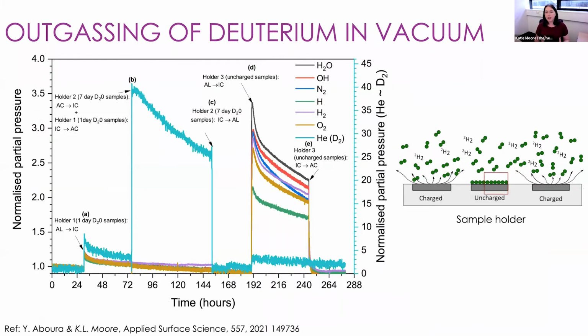As I said, Yasser's project was to really try and look at what we could understand from the NanoSIMS and what we could believe and what we couldn't believe. And I also mentioned at the start that we do not have a cryo stage on the NanoSIMS. So one of our major concerns was that before we could even analyze the sample in the NanoSIMS, all of our deuterium would have disappeared into the vacuum system.